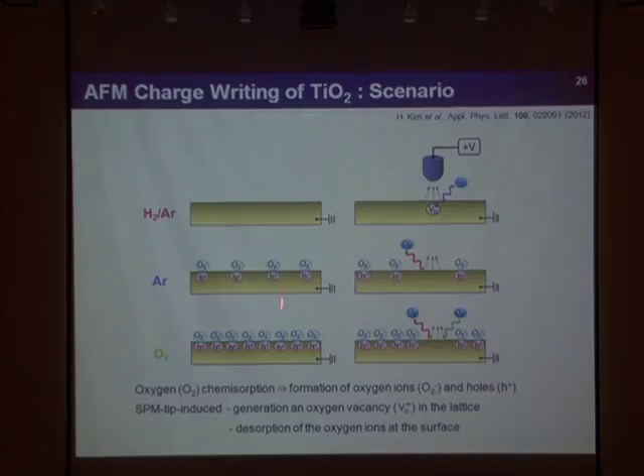This is the initial stage, before. When I apply the positive bias tip, in the first case we might have a chance to remove the oxygen from the sample. But in the latter two cases, maybe we can only remove the absorbed oxygen gases. Especially in the oxygen ambient, there's a lot of chance for reabsorption of oxygen gases, because there are lots of oxygens around.